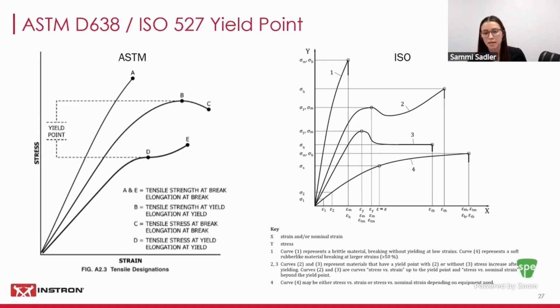From the beginning of the test until that yield point, an extensometer is required by both of these standards to calculate the material's modulus. So it's important that if you're calculating modulus with your material, you must be using an extensometer. These extensometers must meet ISO 9513 class 1 for ISO, and for ASTM, they must meet ASTM E83 class B2.